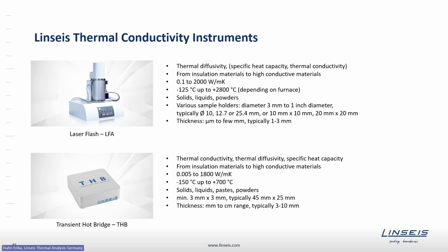The samples are quite small, typically in the range of 10 millimeter to 1 inch diameter, with sample thickness starting from a few hundred micrometers to a few millimeters. Mainly the sample thickness range is between 1 and 3 millimeters. The second transient measurement method we offer in our product range is the transient hot bridge, the THB, which is designed for measuring the thermal conductivity of insulation materials to highly conductive materials. Here too, solids, liquids, pastes, and powders can be determined. The temperature range is a little bit limited, from minus 150 to typically 200 degrees Celsius. With the ceramic version of the sensors, one can go up to 700 degrees Celsius.